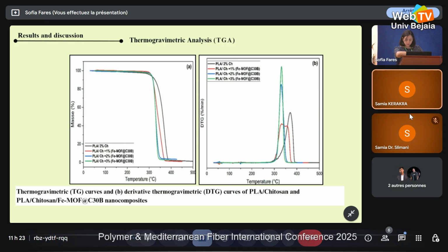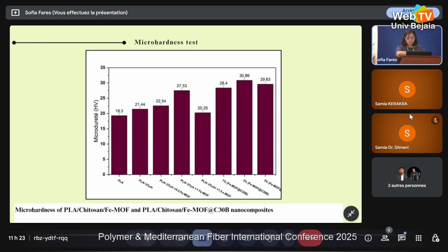Microhardness tests. As this figure shows, the microhardness of PLA-based nanocomposites improves with the Fe-MOF and Fe-MOF@C30B contents. The addition of these fillers enhances rigidity and overall mechanical strength of PLA. The improvement is supported by FTIR analysis, showing hydrogen bonding between the matrix and fillers, which enhances maybe polymer network cohesion and mechanical properties.